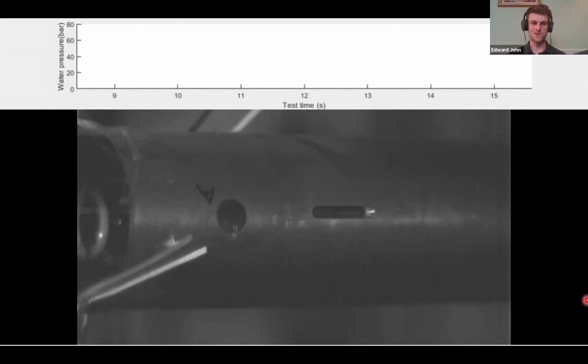This is just because the pit only goes halfway through the pipe wall. In reality, pits probably have to be 90% or deeper to cause high enough stresses. The reason we didn't do that is because manufacturing those pits consistently would have been very difficult. But what matters really is just the stress that the pipe experiences, which you could get through a deeper pit and a lower pressure. So anyway, at the start of the video, there's no leak.